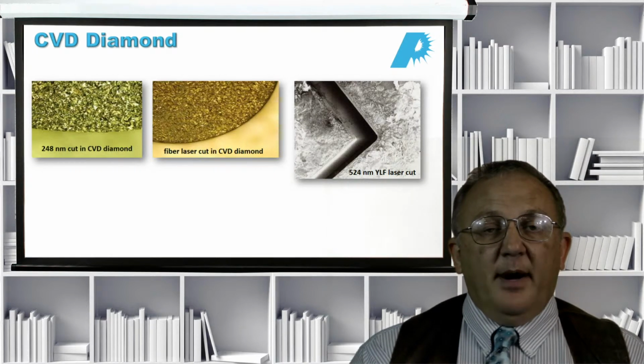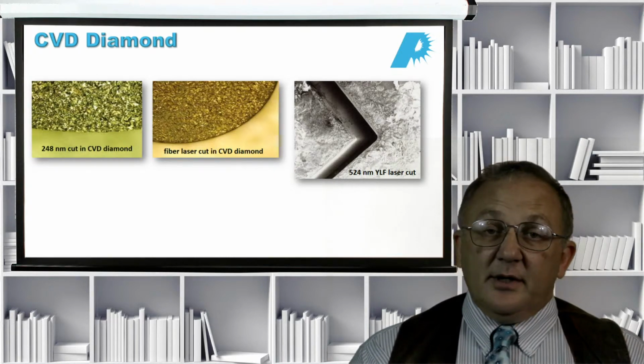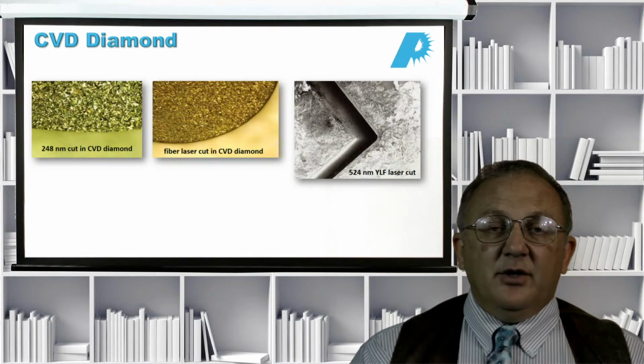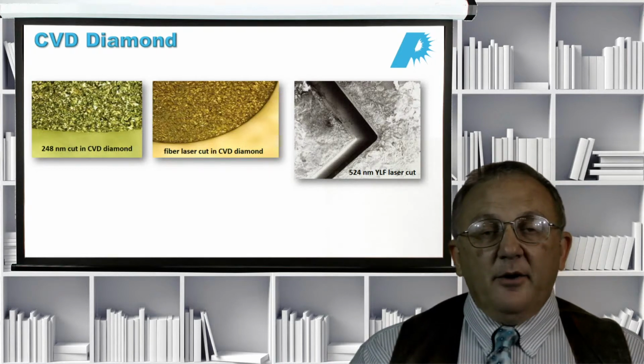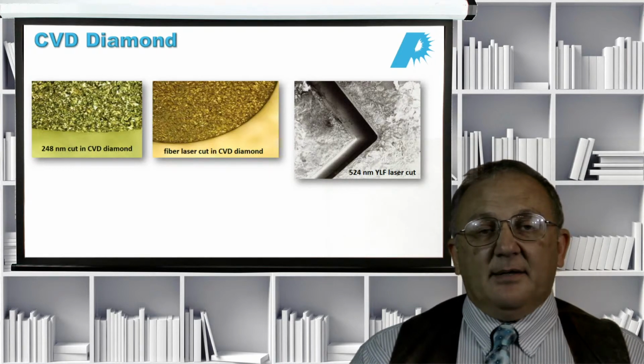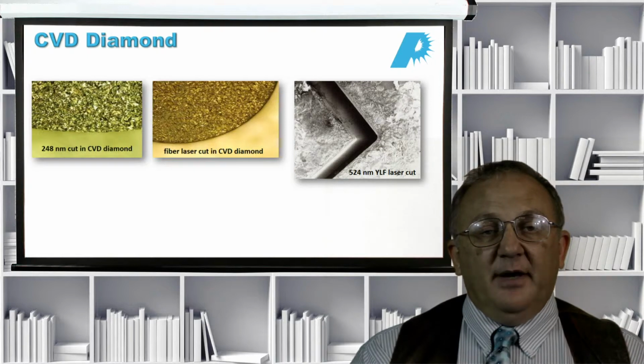That was cut with a 1 micron fiber laser, fairly fast cutting and fairly good quality. You can see that there is a little bit of carbonization around the edges, but in some applications that's acceptable. In other applications, that might not be acceptable, and so on the left-hand side, you see diamond that was cut with a 248 nanometer UV laser.